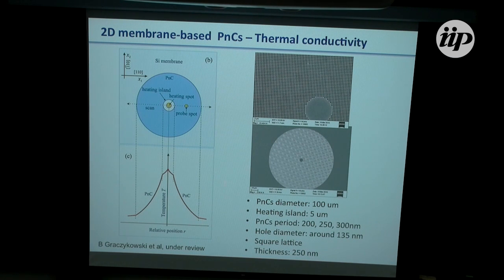The diameter of these phononic crystals is 100 micrometers. The island is 5 microns. The periods are in the few hundreds of nanometers, as in the other case. The hole diameter is in the hundreds of nanometers. Instead of using other geometries, here we use a square lattice, and the thickness of the whole membrane was a quarter of a micrometer.